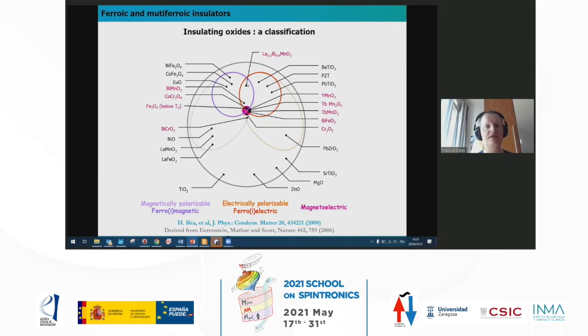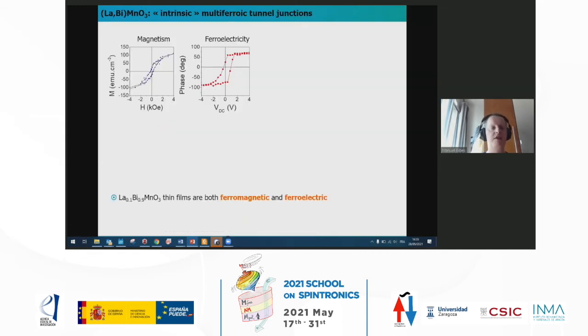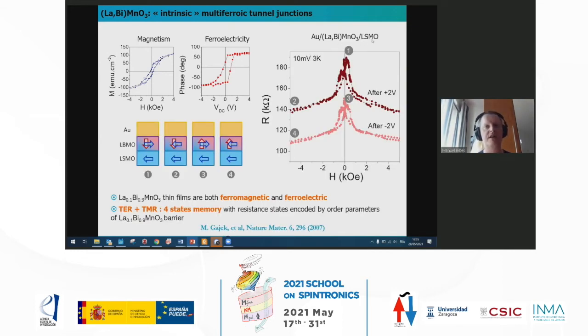And basically we use this, actually it's at the intersection between these purple and orange circles. Okay, so we worked with this compound, lanthanum bismuth manganite, which after a lot of efforts we could show could be at the same time, and even at low thicknesses, compatible with tunneling, ferromagnetic and ferroelectric, as you can see here. And then we used it as a tunnel barrier in our junctions, again with LSMO, and then with gold as the top electrode. And we saw at the same time TMR coming from the spin filtering effect due to the ferromagnetism in the tunneling barrier.